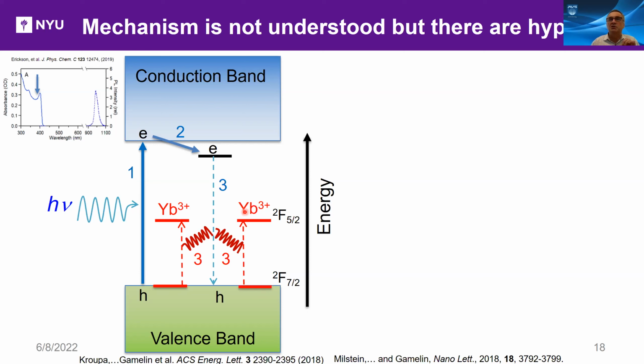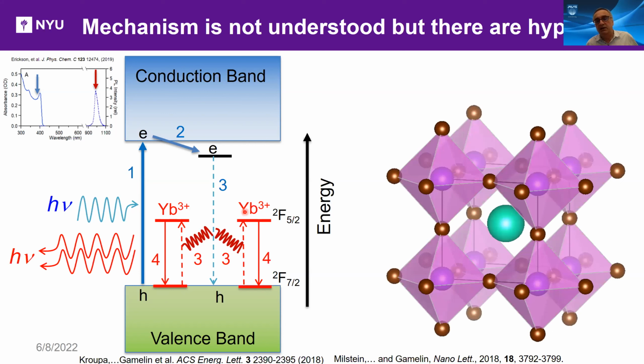If you want a physical picture, this is what we imagine. That's the infrared emission. Here, again, revisiting the perovskite structure, this would be the cesium. These would be the lead atoms and the halide atoms. So here's the lead. If I take out 3 lead atoms and have 3 vacancies, that is 6+ ions I have to replenish. I can put 2 ytterbium, ytterbium is 3+, into 2 of those, and the third one remains. So there is a hypothesis that this is the defect, and it's a charge neutral complex.